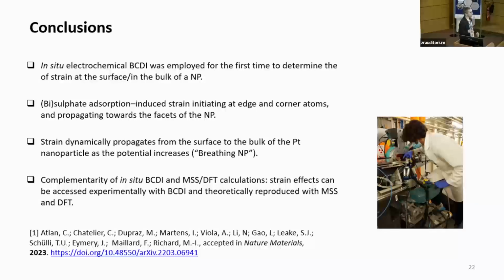We have seen heterogeneities in strain distribution at all scales: atomic scale, surface scale, and differences also between the surface and the bulk. So the particle is literally breathing, electrochemically speaking. So we probably have different reactivity at every different site. And finally, what matters a lot is the complementarity that we have seen between in situ BCDI and the DFT or the molecular static simulations.